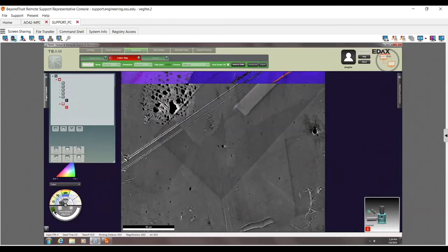Often what I will see is sometimes a bad CI, a good CI, a bad CI. It's often pretty common at low mag if I don't have dynamic focus on. So I basically go into focus and out of focus and into focus again, or the other way around, which is pretty common.